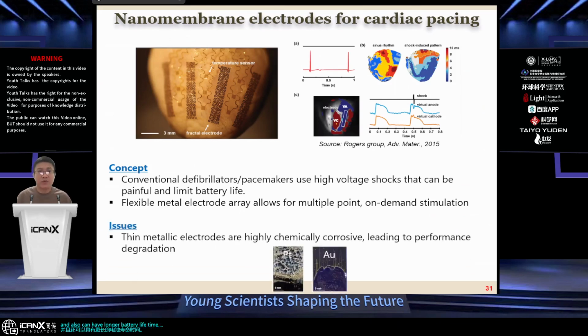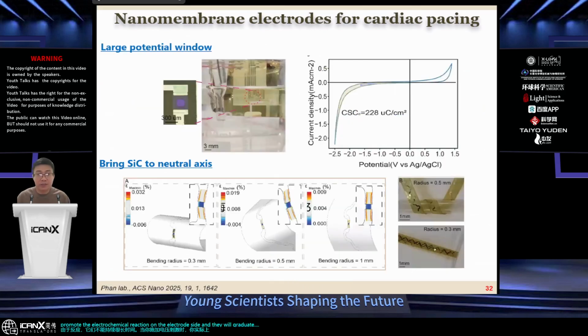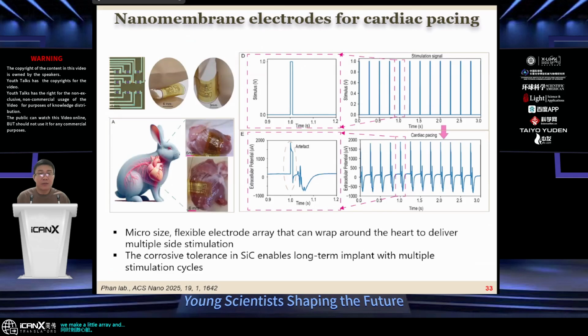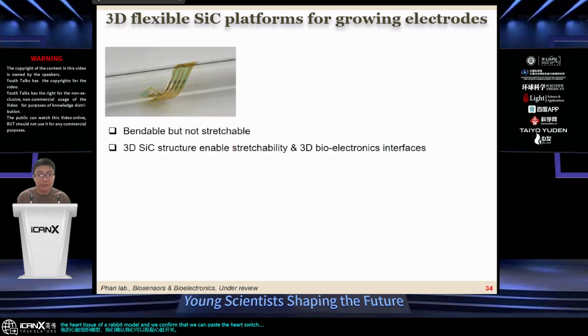But the problem is this kind of flexible electrode patch cannot last very long because of the reaction. When you apply voltage for stimulation, you actually promote electrochemical reaction on the electrode side, and they will gradually degrade. And because our silicon carbide material is chemically inert, and it also has a relatively large potential window, we can use that for simultaneous stimulation of the heart. We made an electrode array and wrapped it around the heart tissue of a rabbit model, and we confirm that we can pace the heart with our regular beat.